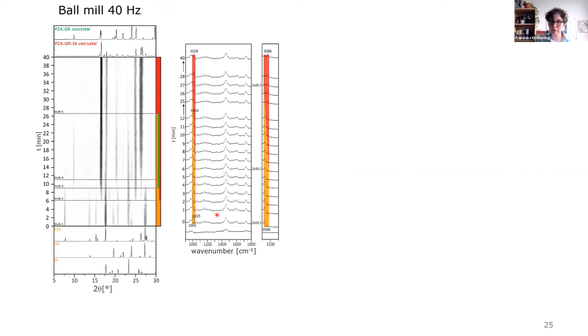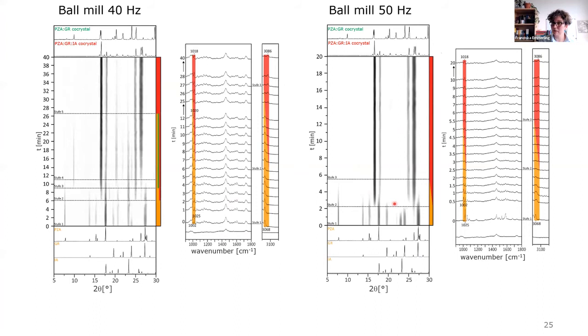So these data are shown for 40 hertz milling time, but if we increase the frequency, and you can see here, then we have a change in the mechanism. So we don't observe the formation of binary compounds, it directly reacts to form the ternary compound. The reaction itself is 6 times faster compared to this reaction under lower frequency, and also the induction period is only a third of the one we would observe under 40 hertz.